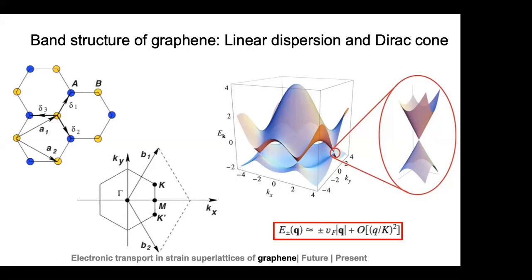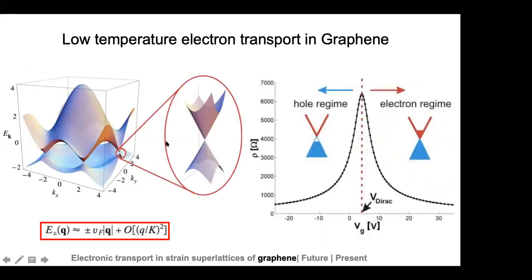So how do the transport characteristics, which essentially refer to the conductivity or the resistivity of the system, vary near this Dirac point? When you're looking close to the Dirac point, you're essentially considering the low energy carrier states, which means that you need to consider low temperature electron transport. Most of these measurements are done at a few kelvins, millikelvins, and so on. In this graph on the right, you can see the resistance of the system plotted against the gate voltage applied to graphene.